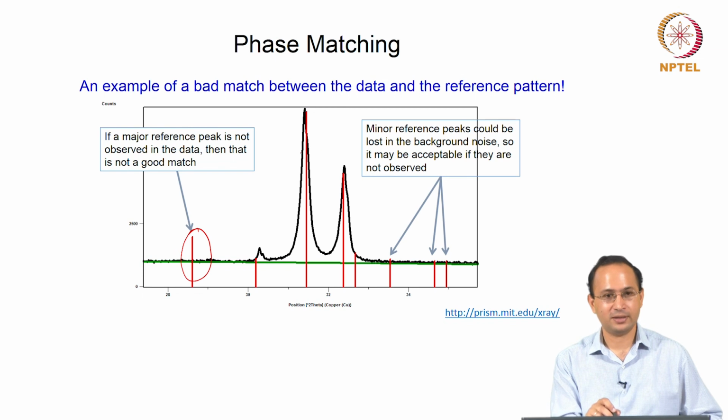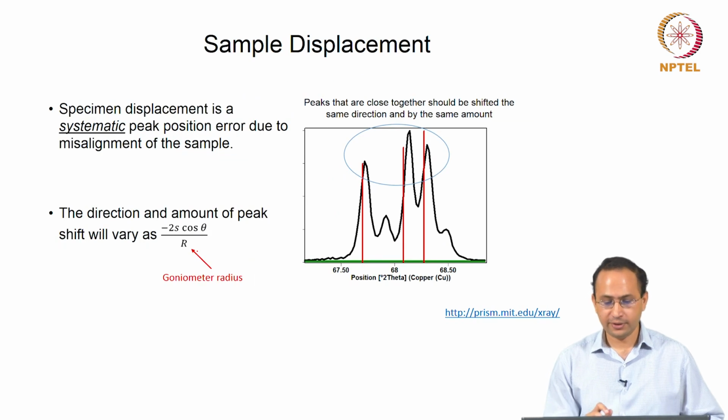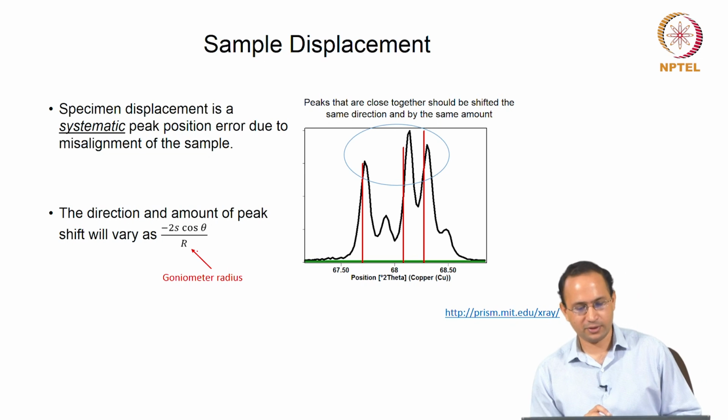Although the peaks are matching, like here you see there is some match, but here this is the third strongest peak, you do not see any match. So, that means there is a problem. These things you have to always check when you do qualitative analysis. Do not rely on just one peak, okay. Another thing, that is where we stopped.